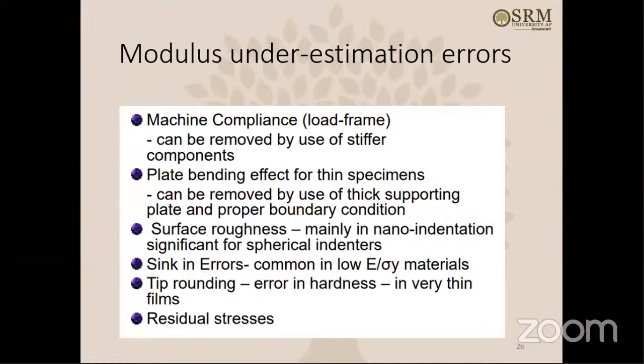Then surface roughness, of course, if you are doing nano indentation, like micro indentation is fine, okay, like millimeters. But if you are doing nano indentation, at the nanometer level, of course, surface roughness matters a lot in those kinds of things, particularly for spherical indenters. If you are doing nano indentation, the surface roughness matters a lot.